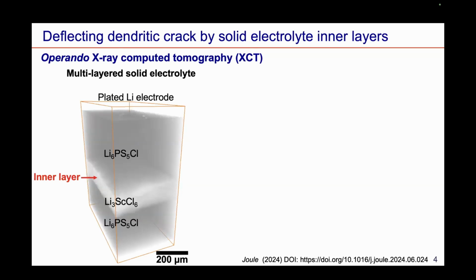We imaged the dendritic crack propagation by synchrotron X-ray computed tomography, or XCT. This three-dimensional rendering is the XCT image of the pristine battery based on this multi-layered structure, with the lithium metal anode at the top. During the test, we charged the battery and induced lithium plating at the top electrode, which induces crack initiation, followed by the propagation of a transverse crack. The crack penetrates across the sulfide layer. When it reaches the inner layer, it is effectively deflected by the inner layer.